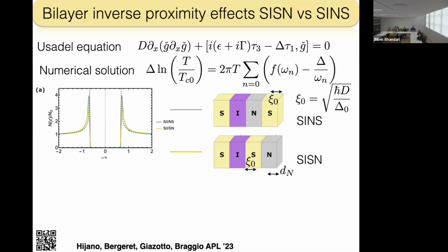So it's a huge thermal gradient, and you can do that because you are working with the electronic degrees of freedom, and the system has all the same temperature on the phononic degrees of freedom. In a certain sense, it's the ideal thermoelectric effect, because the electronic degrees of freedom are at higher temperature, but the phononic ones are all the same. So there is no heat flow to the phononic channel. And this is the advantage, and maybe also the limit.